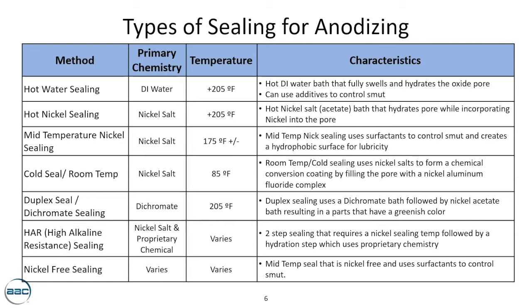Now, with some of this hot water type of sealing, you can use additives to manage the smut, because usually when the immersion times in a bath like this exceed 3 to 4 minutes, as you hydrate, you create smut. And so many anodizers will use an additive to offset that. Hot nickel sealing. This uses a nickel salt. In most cases, it's nickel acetate in a boiling solution with some sort of surfactant. But the intent here is you want to hydrate the pore, and while you're hydrating that pore, you want to allow nickel through a concentration gradient to go into that pore.